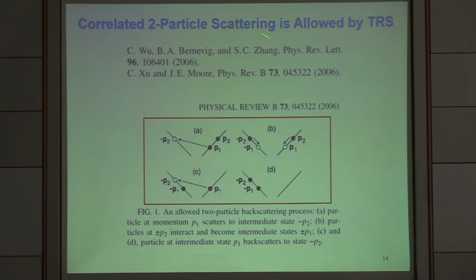Okay. Now, of course, in the interacting case, one can look at what the mechanism for backscattering is. Early on, there were proposals looking at correlated two-particle scattering. This is for the case where there's a strong interaction in the edge state. So the spins are going to flip simultaneously, pairwise. This is protected by time reversal symmetry because it goes simultaneously. Once it goes like this, then the edge state will go back like this. So this in effect opens a channel for backscattering.